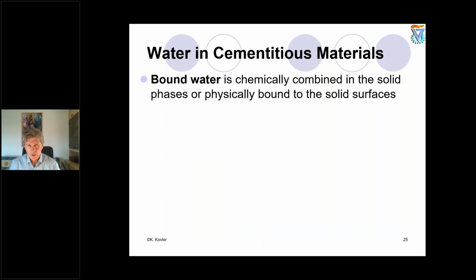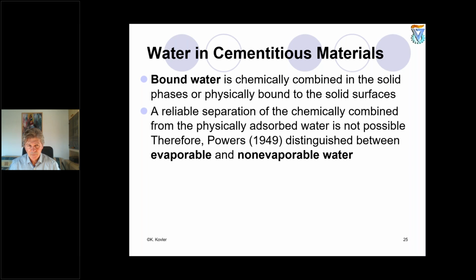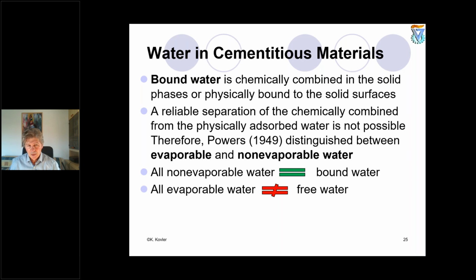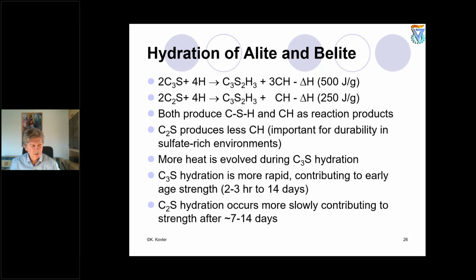Bound water, or chemically bound water, is chemically combined in the solid or physically bound to the solid surfaces. A reliable separation of the chemically combined from physically adsorbed water is not possible, unfortunately. But therefore, Powers in 1949 distinguished between evaporable and non-evaporable water. All non-evaporable water is considered as bound water, and all evaporable water is not necessarily free water. So this is just reminding you the basics coming from the classic work of Powers.